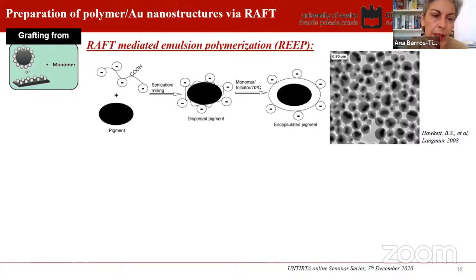So that's why we looked into what had been done before or in the meantime by Hawkett regarding RAFT-mediated emulsion polymerization, which later on was coined as REEP. And these guys used emulsion polymerization combined with RAFT to coat particles. In their case, they coated pigment particles, and they managed to encapsulate them very neatly without having free polymer, or at least not much free polymer around. And this was exactly what we wanted.